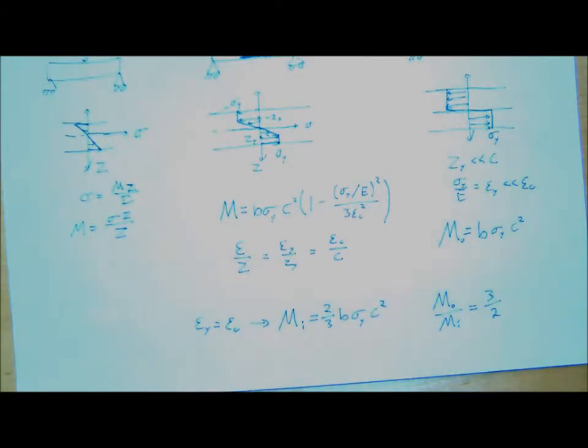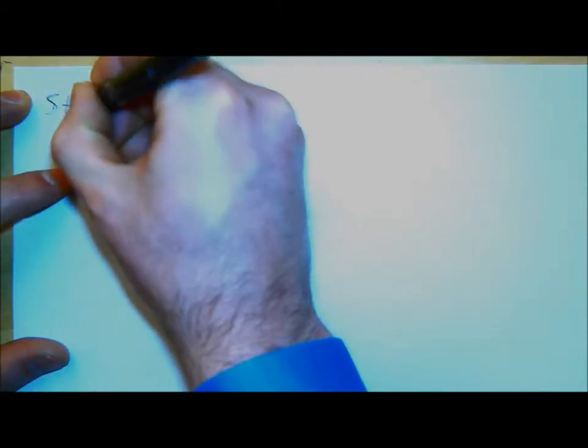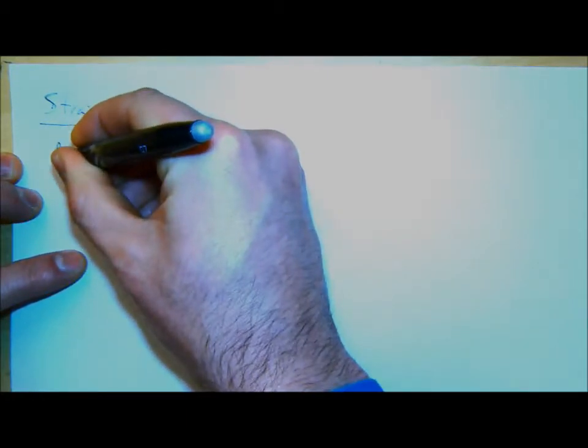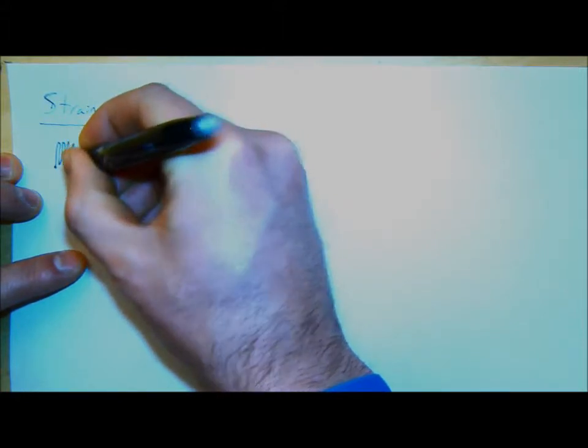The other topic covered in the lecture notes posted was strain gauges — probably a little bit more important for the beam bending lab. A strain gauge is a metal device with an accordion pattern. When you apply axial strain along the axis of that accordion pattern, it causes a change in resistance in the material. That's a property of the metal being used.